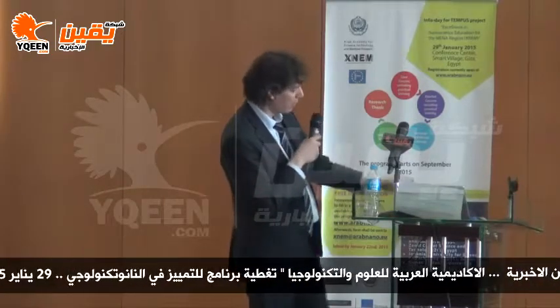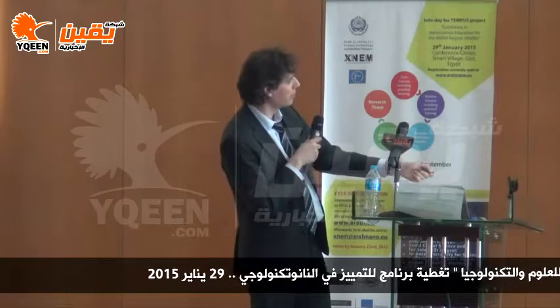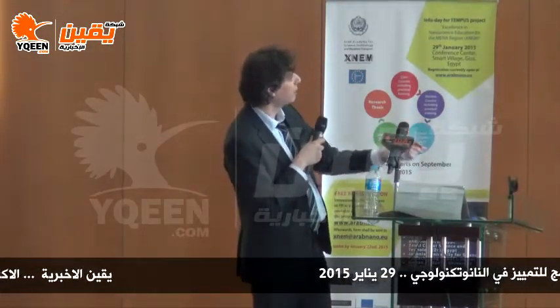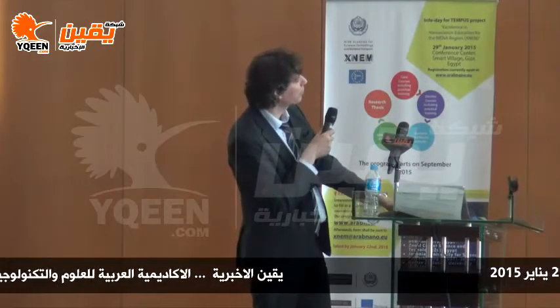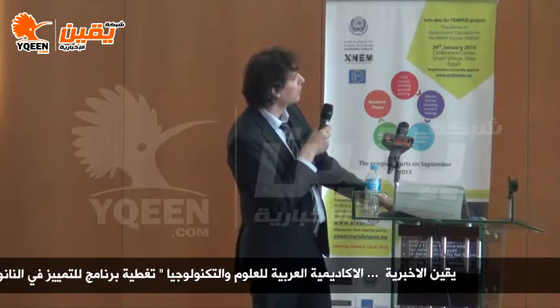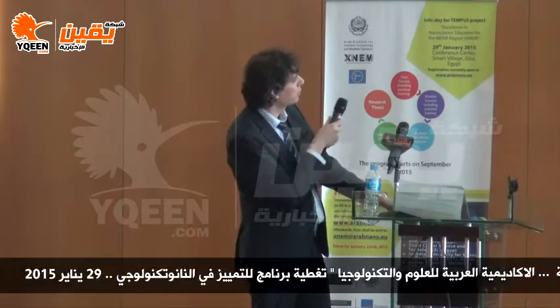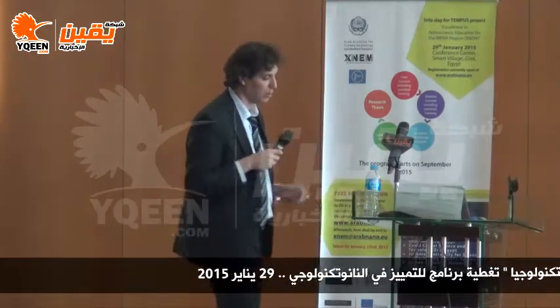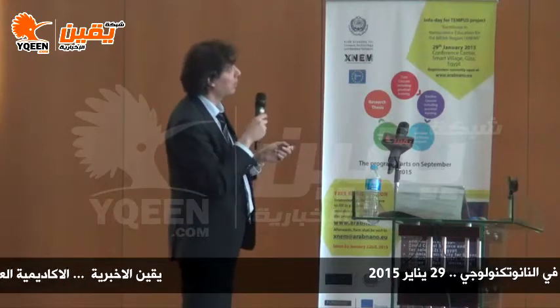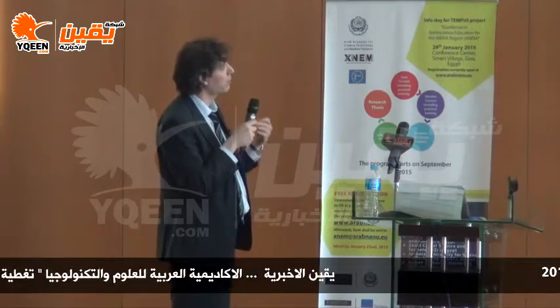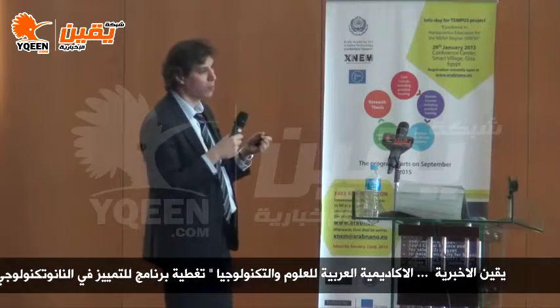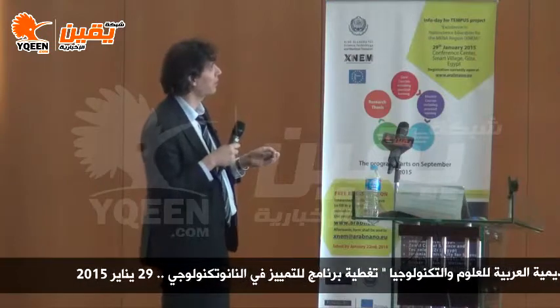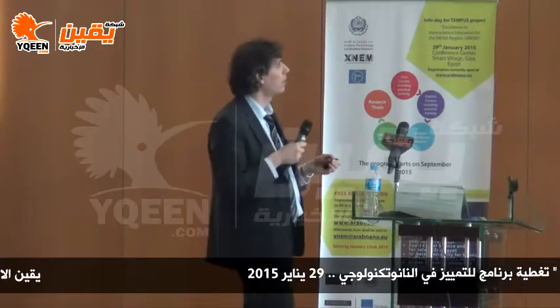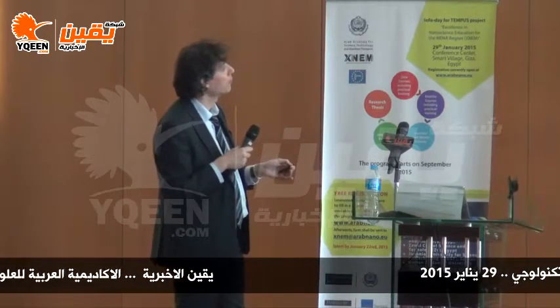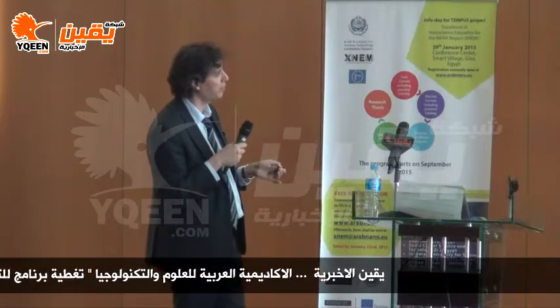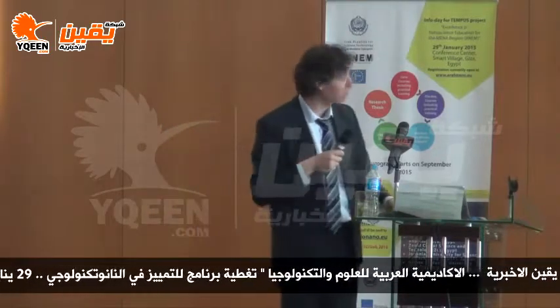Here, these are just IV characteristics that we fit with different models to extract the transport mechanism. That's also something important that you can extract from the IV characteristics. And again, we also did the same work with the undoped diamond. I will go a little bit faster, but just to show that we can also optimize the undoped diamond. So the objective was the fabrication of a UV photodetector based on diamond. As grown, the diamond is not satisfactory, so we had to change the surface state. Our strategy was to use ozone exposure onto the diamond. So we managed to remove the high surface conductivity and create surface states in order to improve the responsivity of the devices.